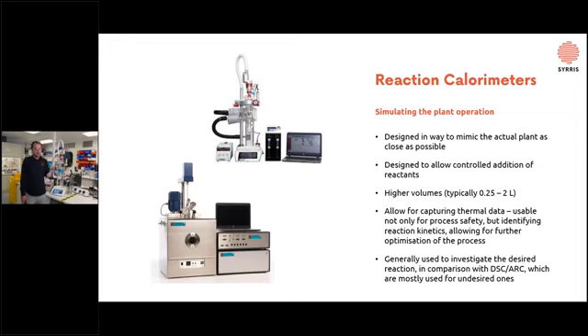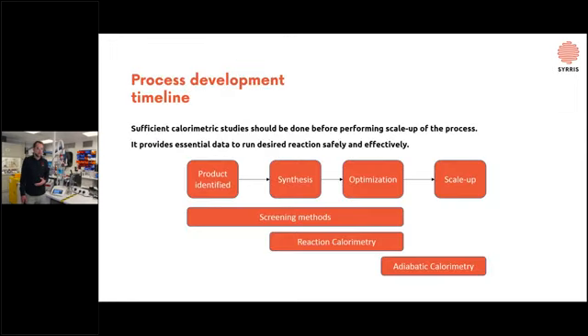So if we go back to our schematic, where do they fit? I actually removed the production scale because we wouldn't use calorimetry on a production scale. During the first 3 phases, we would use screening methods such as the DSC, really to identify the physical properties of our compounds, reagents, their heat capacity, their decomposition temperature, and basically their behavior at higher temperatures.